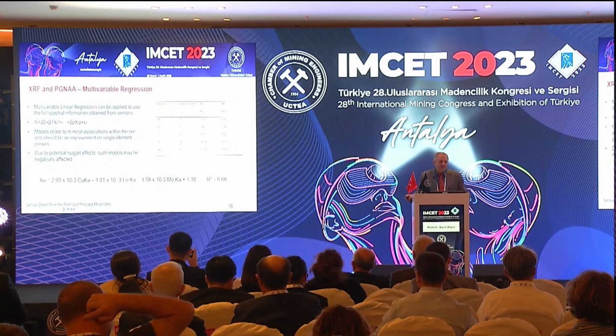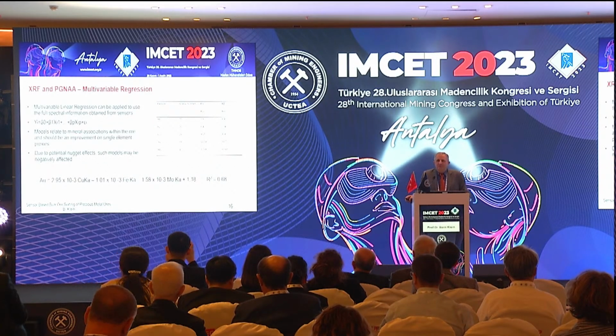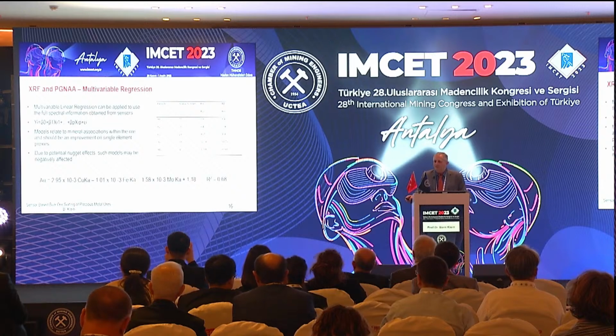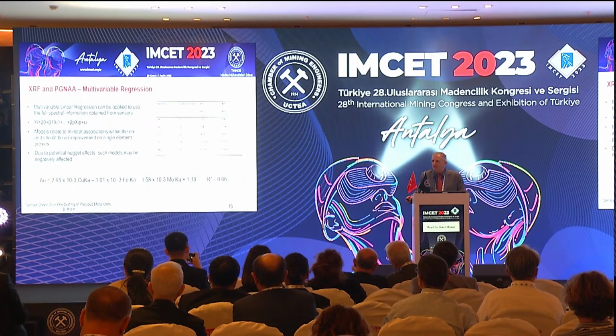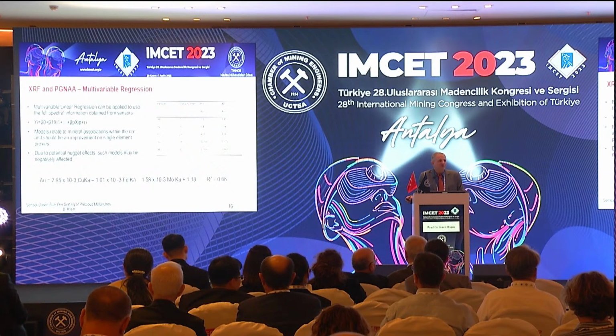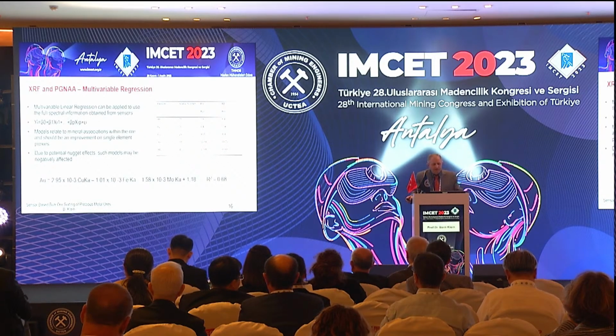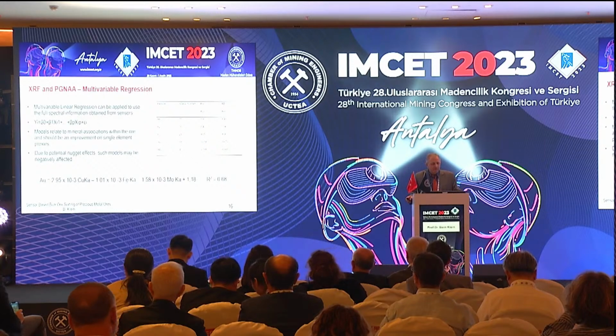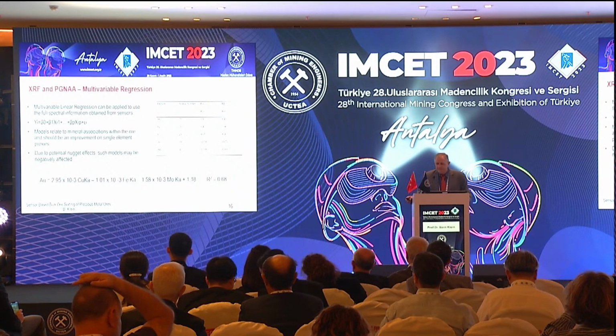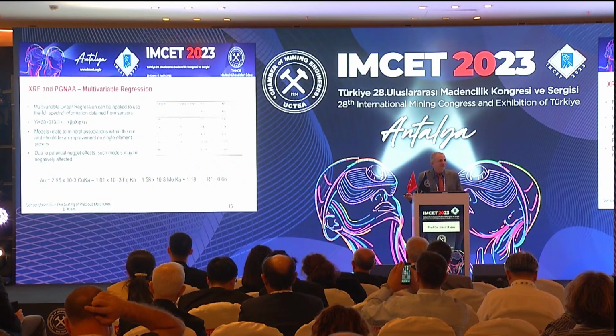Multivariable regression, as mentioned, you can develop models that incorporate all of the information from the sensor, whether it's XRF or PGNAA, and probably magnetic resonance if you can identify more than one mineral. And you can put that into a simple model as shown on the bottom there in order to come up with a predictor for gold grade. Again, this is not a stellar example. The R-squared was only 0.68 here.